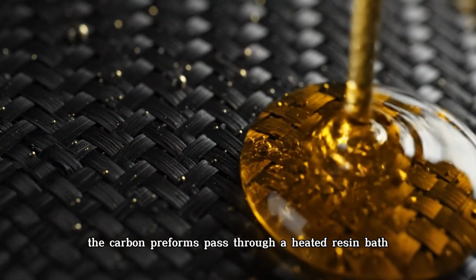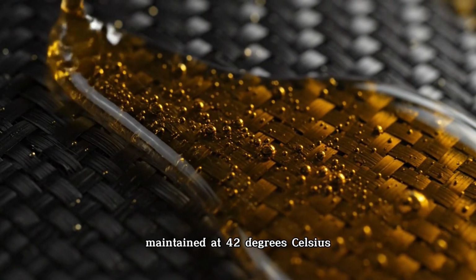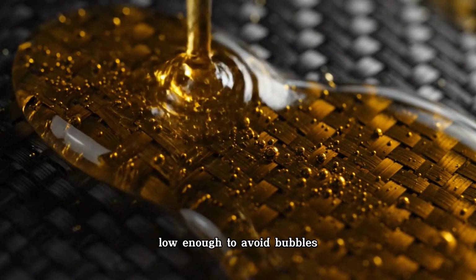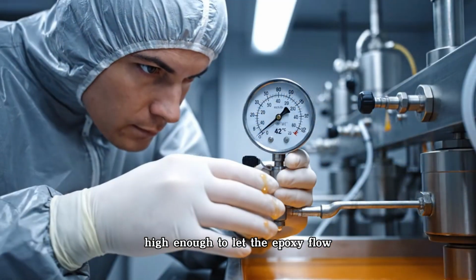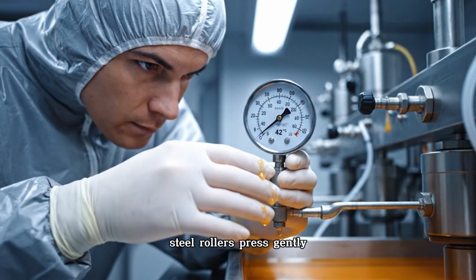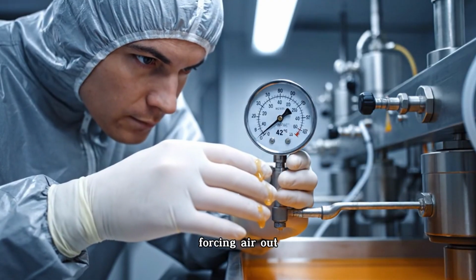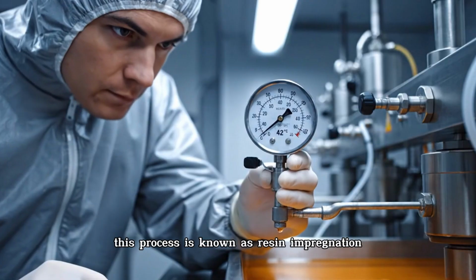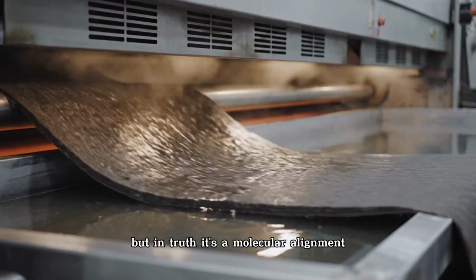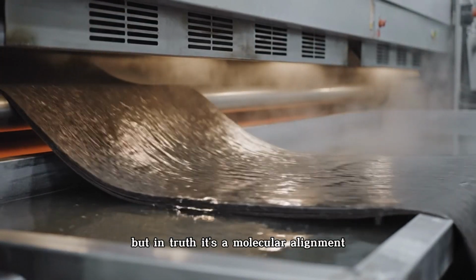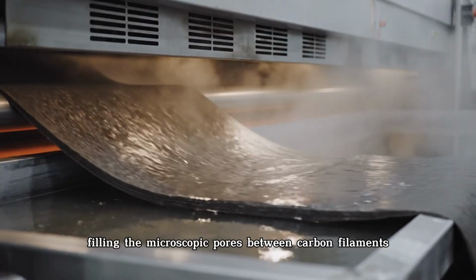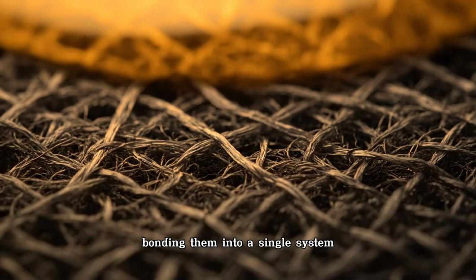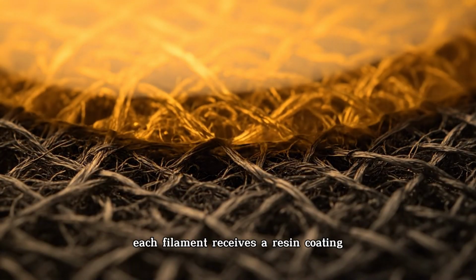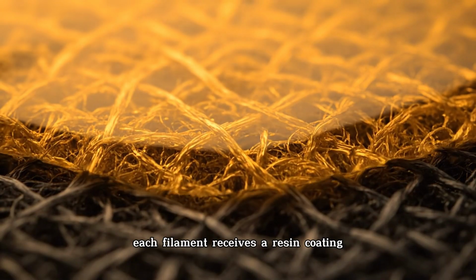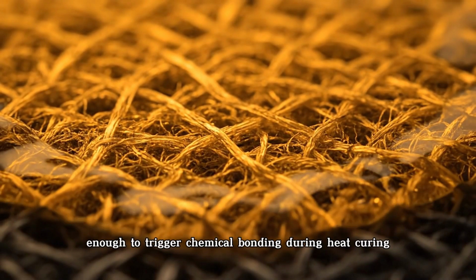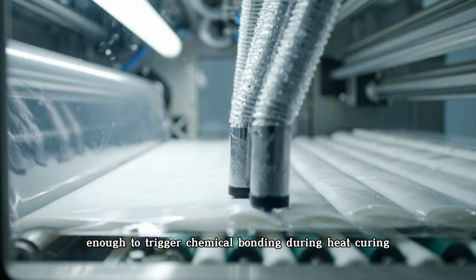The carbon preforms pass through a heated resin bath maintained at 42 degrees Celsius, low enough to avoid bubbles, high enough to let the epoxy flow. Steel rollers press gently, forcing air out. This process is known as resin impregnation. But in truth, it's a molecular alignment, epoxy filling the microscopic pores between carbon filaments, bonding them into a single system. Each filament receives a resin coating only 10 microns thick, enough to trigger chemical bonding during heat curing.